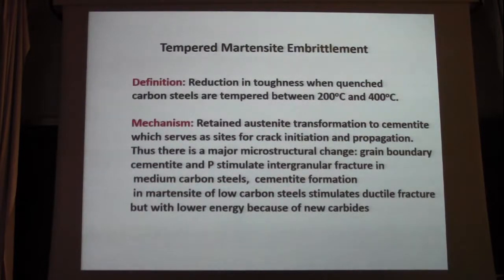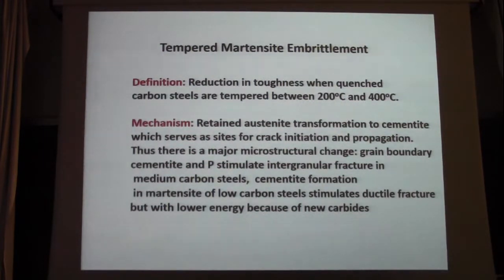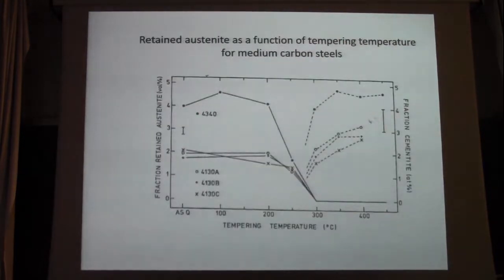So, tempered martensite embrittlement: reduction in toughness when quenched carbon steels are tempered at higher temperatures, between 200 and 400 degrees C. And what's happening in the microstructure is that the retained austenite transforms by diffusion to cementite. And the cementite serves as sites for crack initiation on grain boundaries and within the structure, basically. So this is tempered martensite embrittlement.